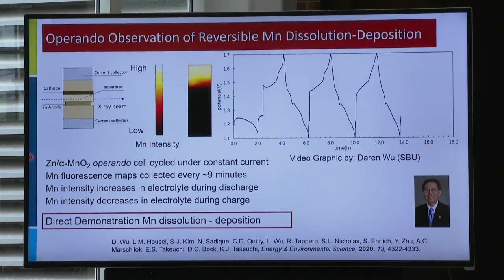So the next step was actually to cycle a battery while we were doing the microfluorescence maps. And unfortunately, my video, I checked it earlier, doesn't work, but let me describe. What we're able to see is as the battery discharges and charges, we could see the manganese intensity in the electrolyte layer increase during discharge and decrease during charge. So this not only said that manganese dissolution is a key part of the electrochemistry, but deposition is as well.